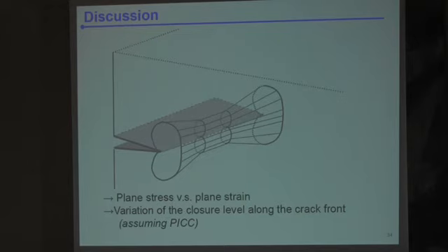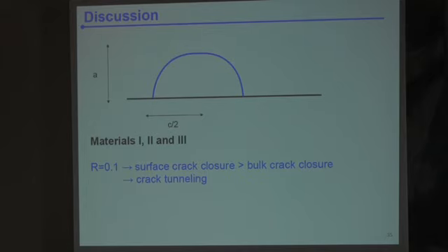This is a well-known picture of the plastic zone close to the crack tip in a through crack in that case, which is smaller in the bulk and larger at the surface because you go from plane strain to plane stress. And this is very well known, in fact, and when you grow this crack in a CT sample, you get crack tunneling. All of you know that. And the crack at the surface is held back by larger crack closure. There is less evidence of this on part-through cracks. There are a few data on aluminum alloys, but not much. And we believe that this is what we have here.